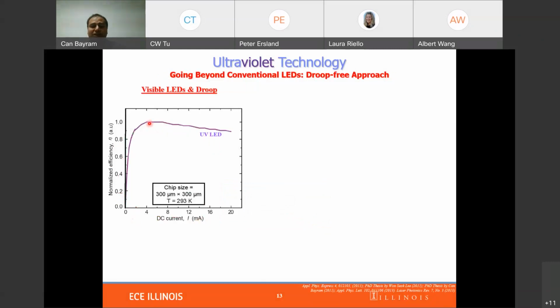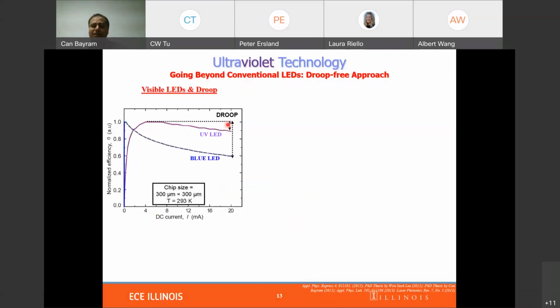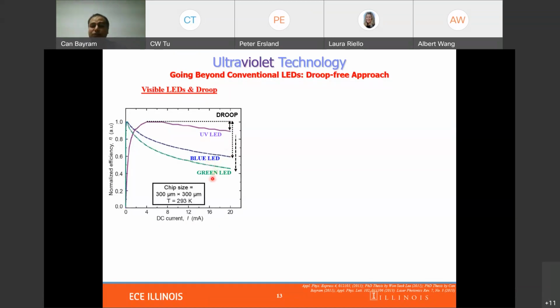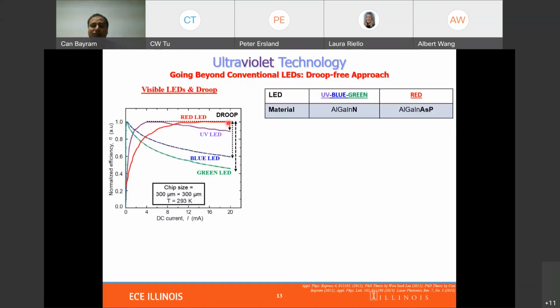Now, when we look into this, we see that the efficiency peaks under low current densities, and the efficiency drops when we increase the injection. This is called efficiency droop. If we look at blue LEDs where we use more indium rather than aluminum, or green LEDs where we use more indium, we see that the droop just increases. Now, if you look into red LEDs based on arsenide phosphide technology, we do not see similar effects under these injection levels. So what's the difference?